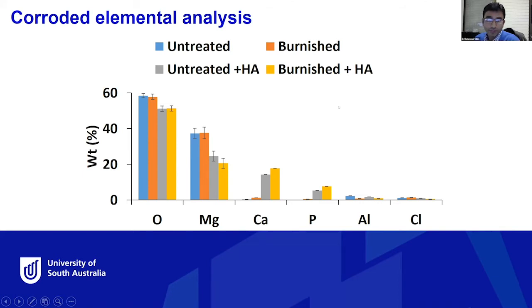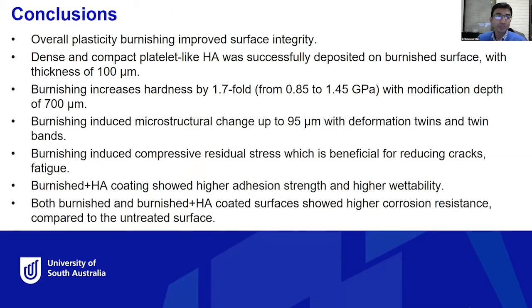So finally, just to conclude, I would like to show that burnishing is going to improve the surface integrity in general, and we can deposit a very dense and compact flake-like HA coating onto the burnished surface, with a thickness of 100 micrometers. Burnishing not only increases the HA coating deposition, but also increases the hardness at the top surface. It also induced microstructural change up to a 95 micron depth with some twins and twin bands, which we believe is going to increase the surface activation energy that allows the HA coating to be deposited successfully.